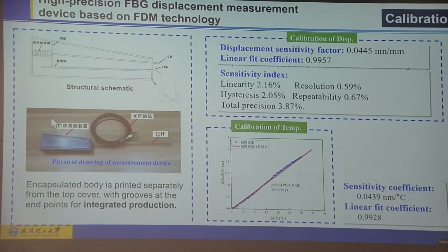And then finally, we developed this device. This device we fabricated in our lab. This is the rod. You can change the deformation, the length, and the diameters. And also you can change the spring, so you can get different measurement ranges. So also we do some calibration tests. We find the displacement sensitivity and also the sensitivity index of these different transducers.